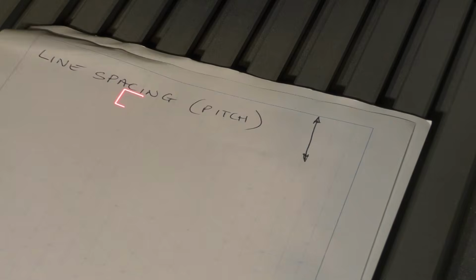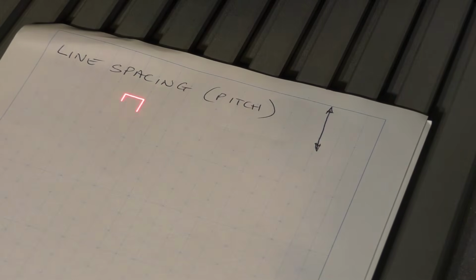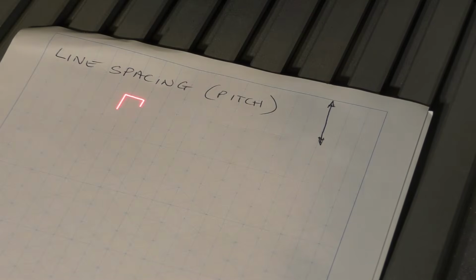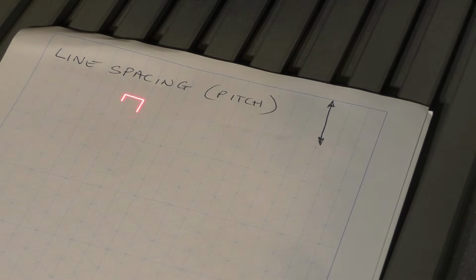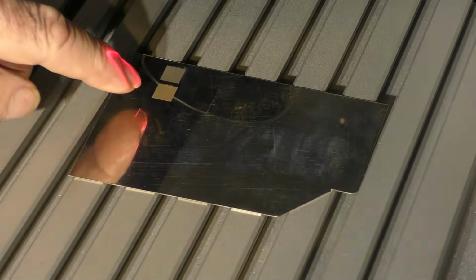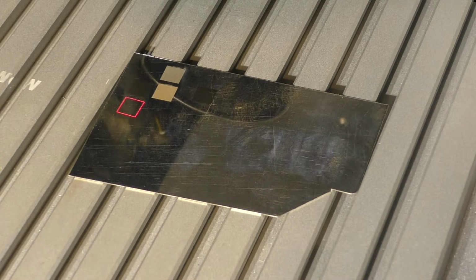If we want to change the power in the vertical direction, we have the opportunity to do that as well. If we're doing engraving, which we are most of the time because this is a scanning engraving machine, then we have the opportunity to play with the line spacing this way, the pitch between the lines. At the moment on this test patch I'm using 100 micron spacing. I've got a 60 micron beam on here, and so effectively there's dead space between the lines that you're looking at on this pattern here. You can't see that because your eye is just not capable of looking at that resolution. We shall see it under the microscope, but not with your eye.